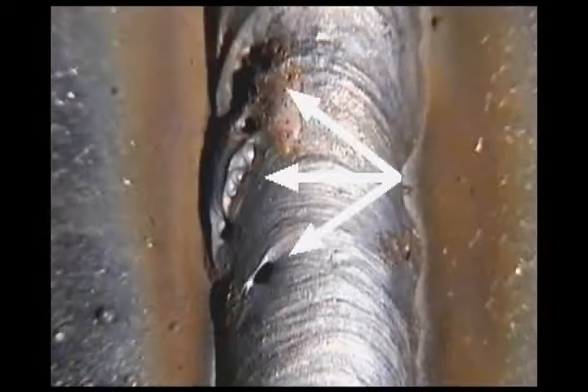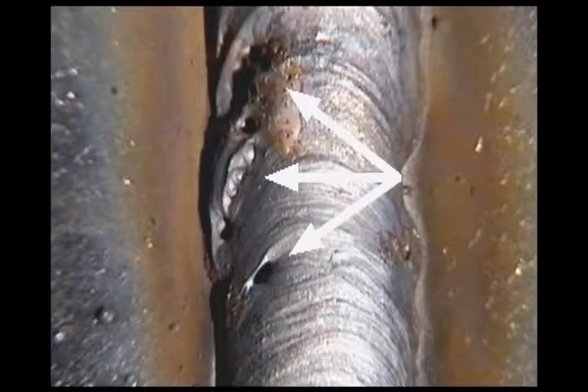Surface impurities will often cause little gas pockets, which is porosity, in the finished weld bead. Impurities also take the heat that should be going to the base metal, limiting weld fusion, especially at the edges, because the metal doesn't get hot enough to melt. In many situations, you'll find that it takes longer to get the metal ready to weld than it does to